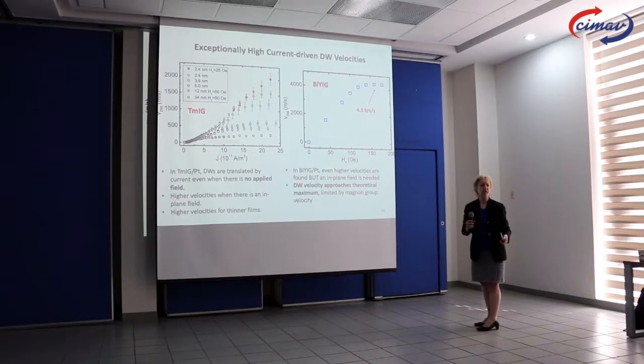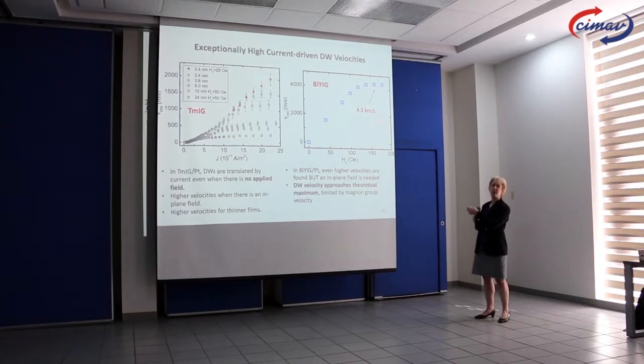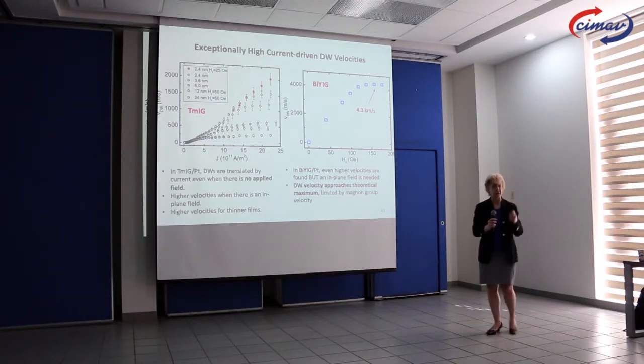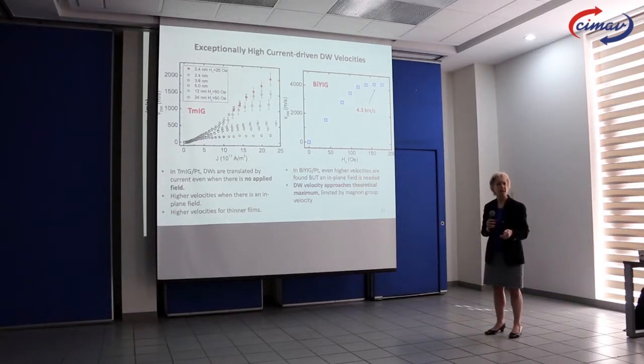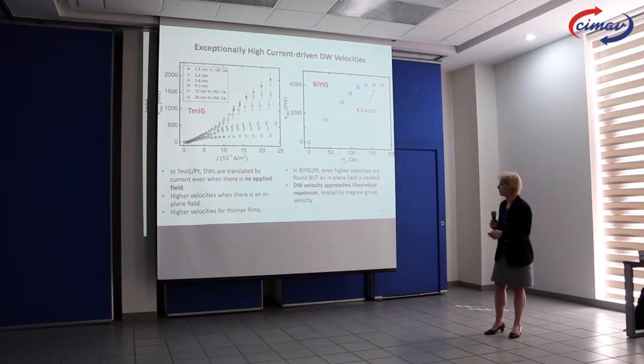And the big question is, how fast will it go? So it turns out the answer is extremely fast. And this here is the speed of the domain wall in a bismuth-YIG film. It's nearly 4.3 kilometers per second, which is pretty amazing. So this is actually the fastest domain wall velocity reported.